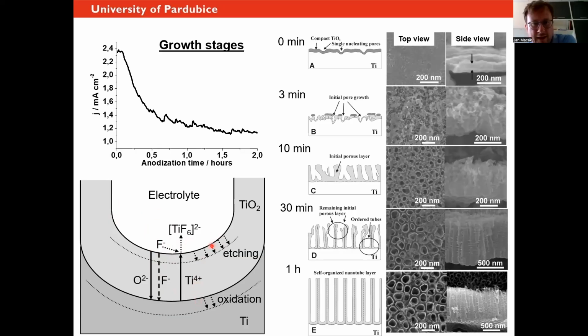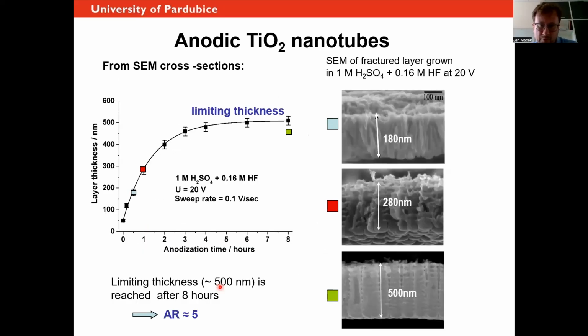So once you understand this equilibrium between the etching and oxidation, you are able to come up with something which looks like this. So you realize that after a few hours of anodization in HF, you get a limiting thickness and you can't get thicker, no matter how long you anodize.